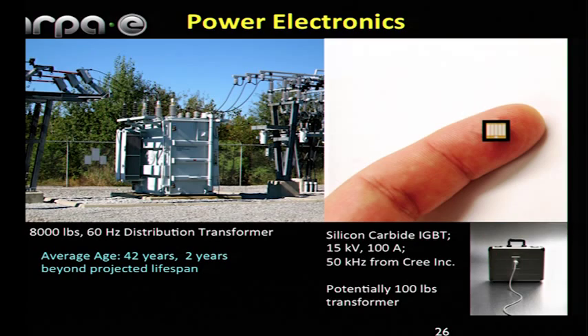this electronic form. This is the company called Cree, which is making silicon carbide-based transistors, and this came out of an ARPA-E project, where a single transistor could drop 15 kilovolts of voltage across a 200 micron thick layer of silicon carbide. So the material quality has to be really good. You can't have dislocations and resistance, because then you have latch up in these transistors. And it can handle 100 amps. So 1.5 megawatts of power being switched at 50 kilohertz going through a fingertip. That's equivalent to 200 homes.